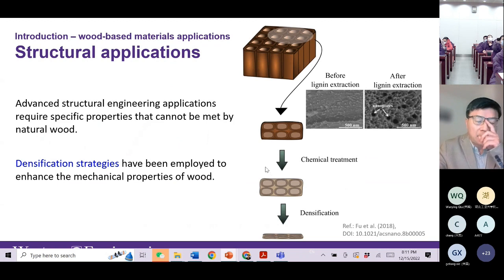In terms of structural application, we have one strategy, which is commonly used by many scientists and by much of the industry now. This strategy is to remove the lignin first. So extract the lignin, remove lignin, then open the pores. Then densify these fibers. So after lignin is removed, the wood becomes porous, and then you densify that to make very condensed fibers. And after densification, this densified wood provides strong strength.